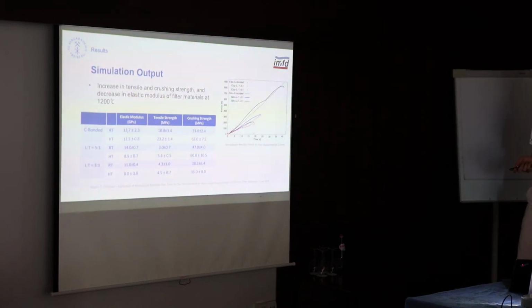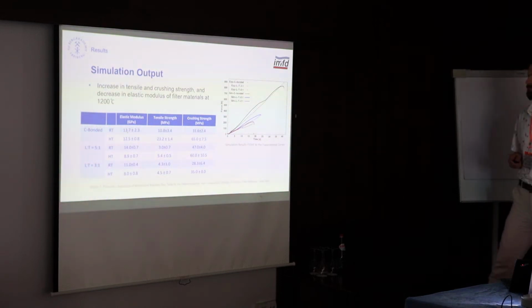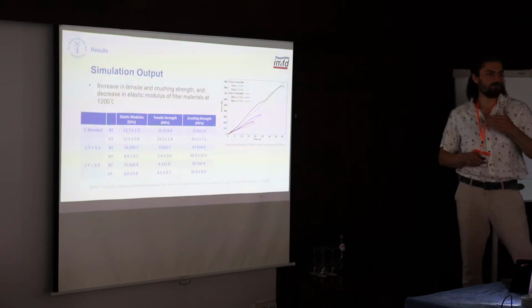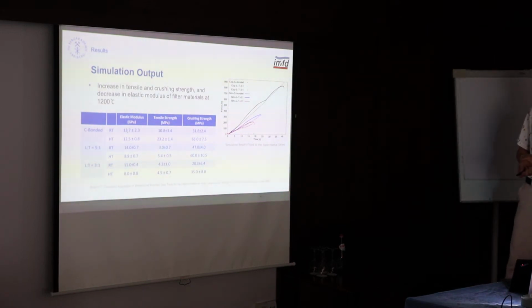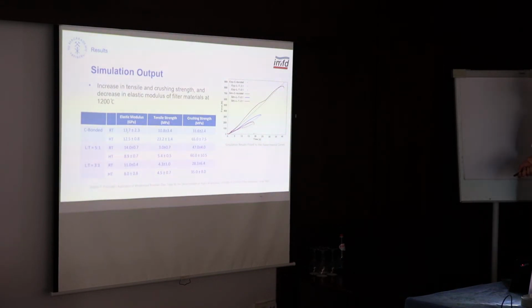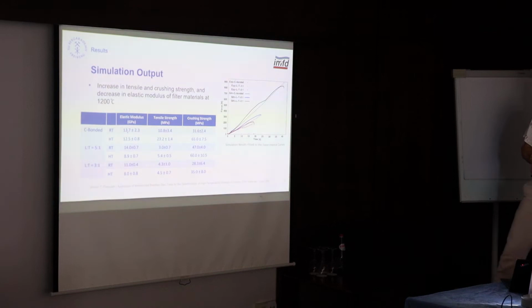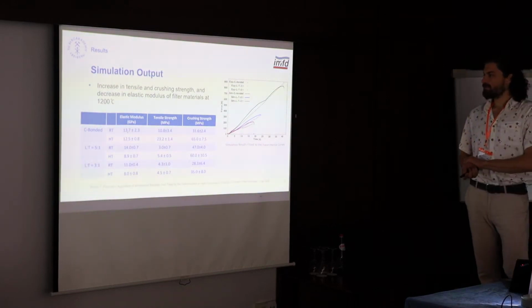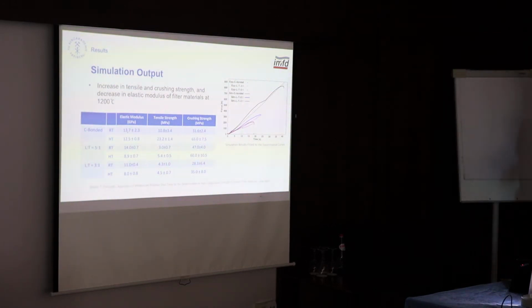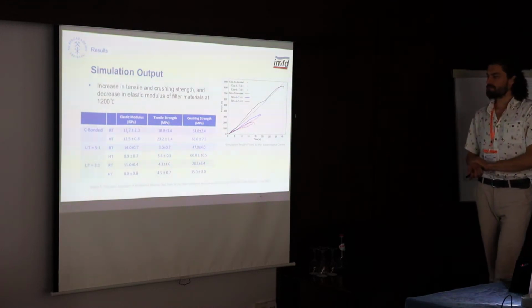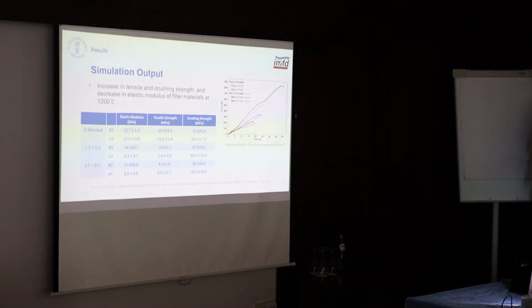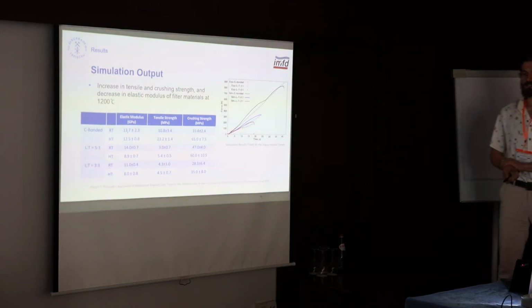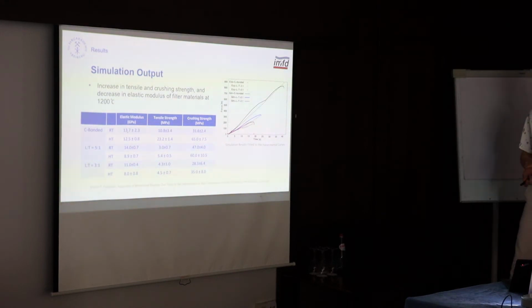And later, by adjusting the cohesive parameters, I was able to fit my simulation data to the experimental data, and doing that, I obtained the elastic modulus, tensile strength, and crushing strength. So you see that there's a drop in elastic modulus and increase in tensile and crushing strength of the material at 1200 degrees Celsius in comparison to room temperature.